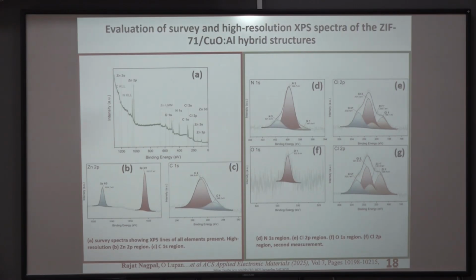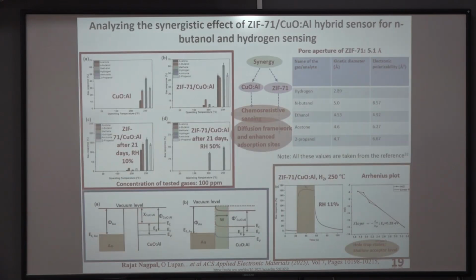To get insights about chemical information, in the X-ray spectra we can see the surface scan spectra confirms the presence of photoelectron lines associated with the ZIF-71 hybrids, and high resolution spectra confirms the chemical bonding environment of different species. Nitrogen has 3 different chemical bonding environments, Cl 2p, it confirms its spin orbit splitting and deconvoluted peaks, and zinc 2p coming from ZIF-71, its 2+ oxidation state is confirmed.